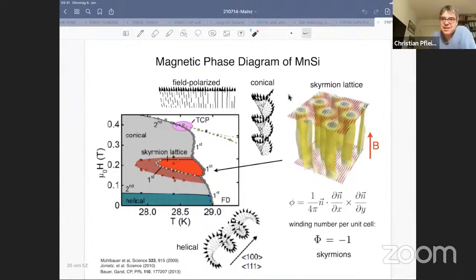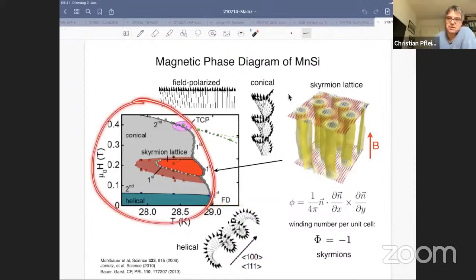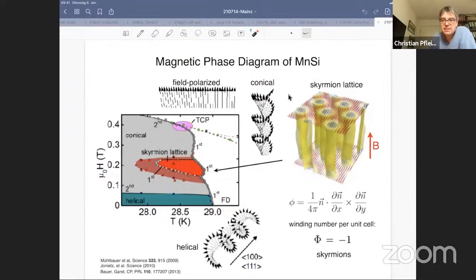So this is the one slide alluding to the skyrmions. MnSi, when it orders at 30 Kelvin, displays this complex magnetic state, which develops this magnetic modulation. And when you apply a small field, you get the skyrmion phase, which is shown here, in a small phase pocket. So this is a completely different line of work. One of the things that came out of this work is that you see an additional contribution to the Hall effect in the skyrmion lattice phase. This is something we call the topological Hall effect.